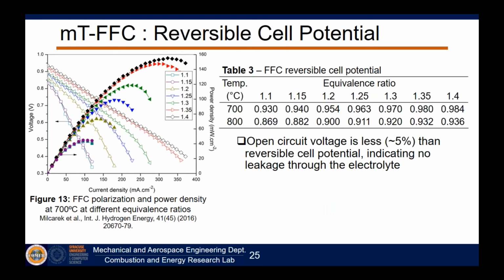Ultimately, what we find is that once we go through those calculations, we can predict theoretically a voltage between about 0.93 and 0.98 volts. Well, if you take into account that there are actually some irreversible losses in the fuel cell, we find pretty good agreement within about 5%. So that's irreversibility at open circuit voltage. So you can actually predict some things about this system just using thermodynamics.